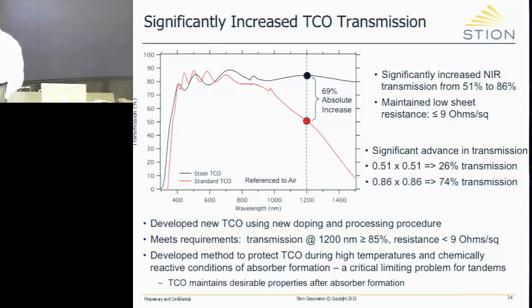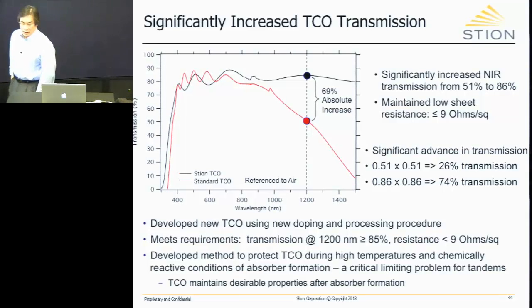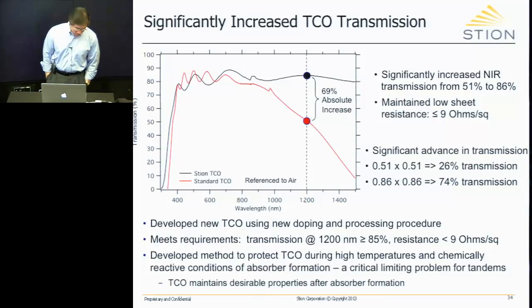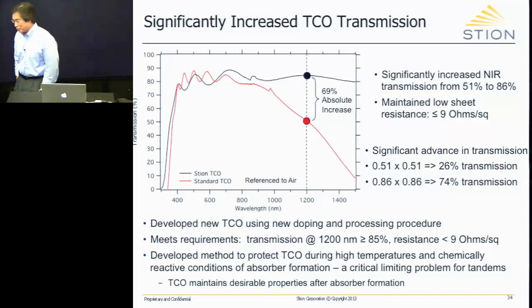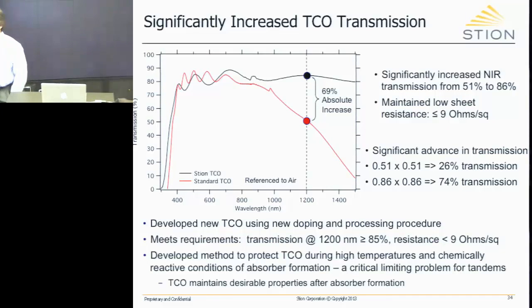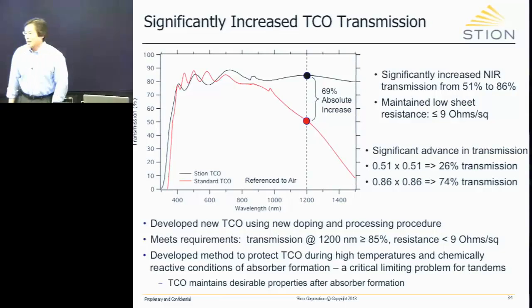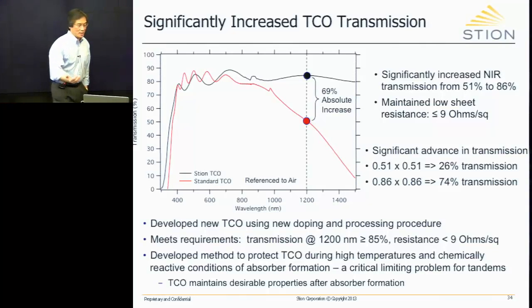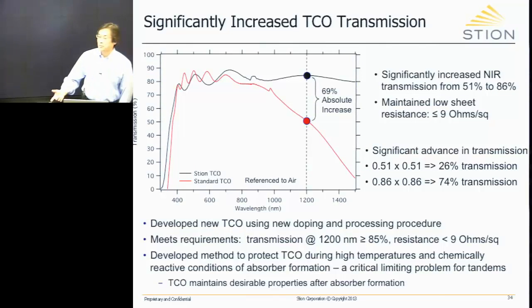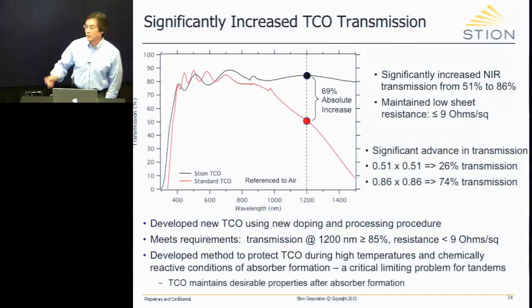Actually, that's a great question. We're not using soda-lime glass for that. We're using what's called water-white glass. It turns out that nature is very, very cruel, because soda-lime glass is very inexpensive, but it contains iron. And iron has an absorption right there. So we use water-white glass where the iron is leached out. It's a little bit more expensive, but when we go to high volume, they're comparable.